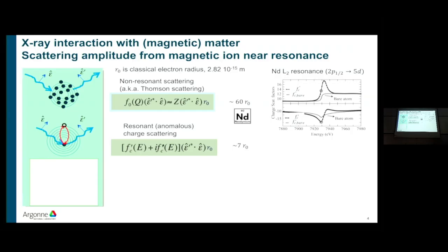Now, when you get near resonances, things change. You know we have X-ray absorption near resonances, and here we have an absorption edge near the neodymium L2 resonance, which is a 2p1/2 core level excitation. So obviously these X-rays are getting absorbed, so less X-rays are getting scattered, and there is a modification or an addition to the scattering cross-section, which is captured by these complex scattering factors.